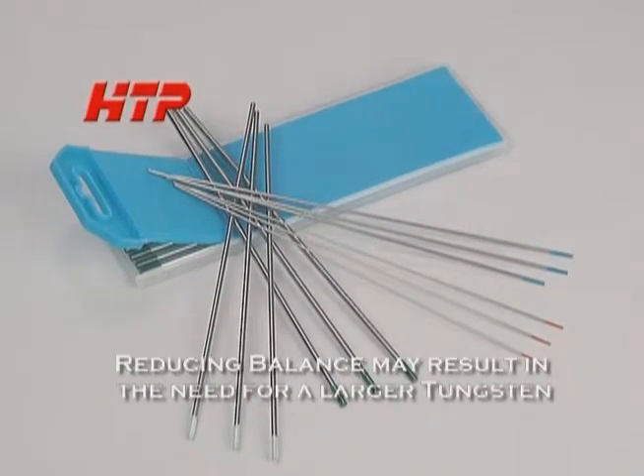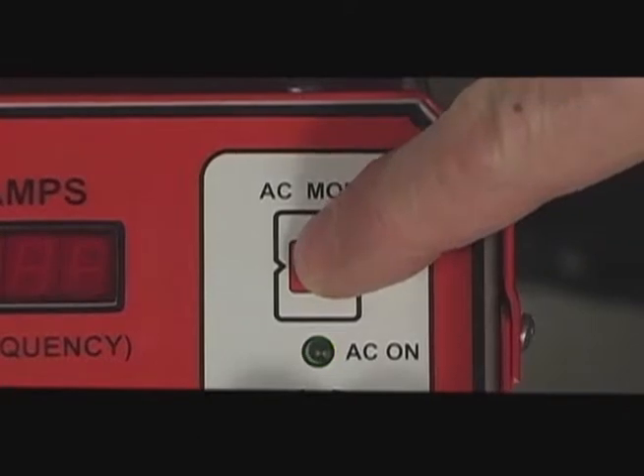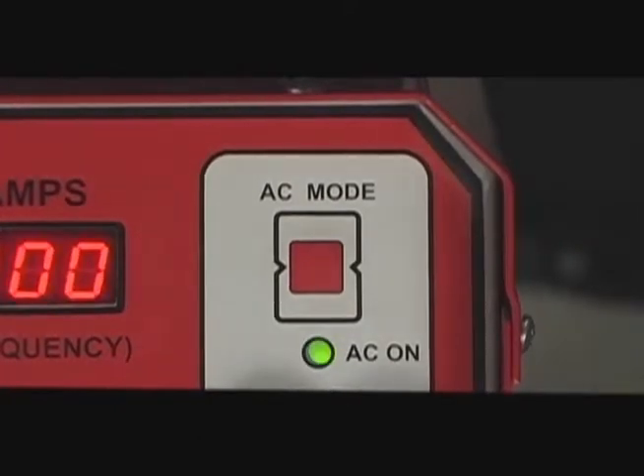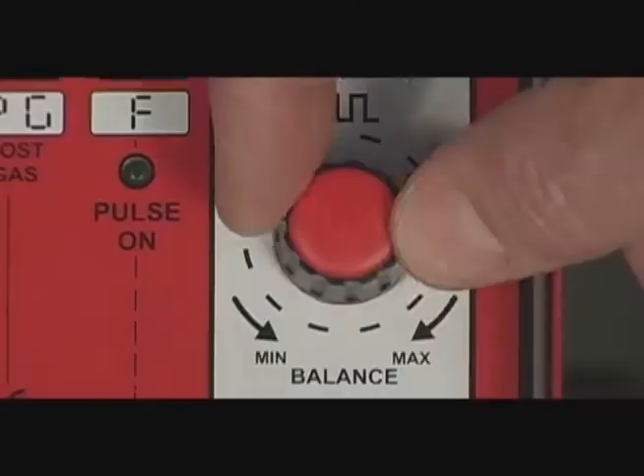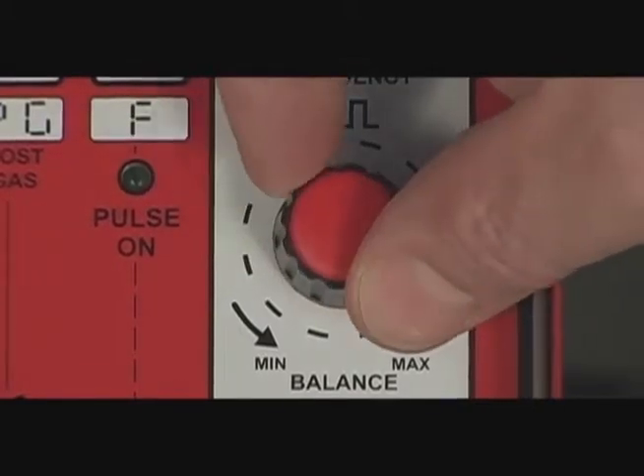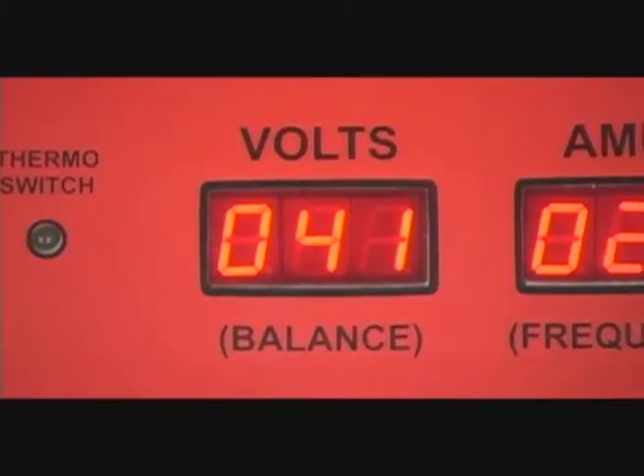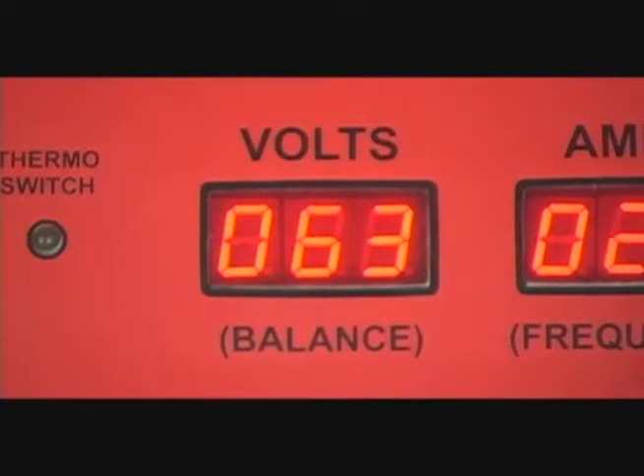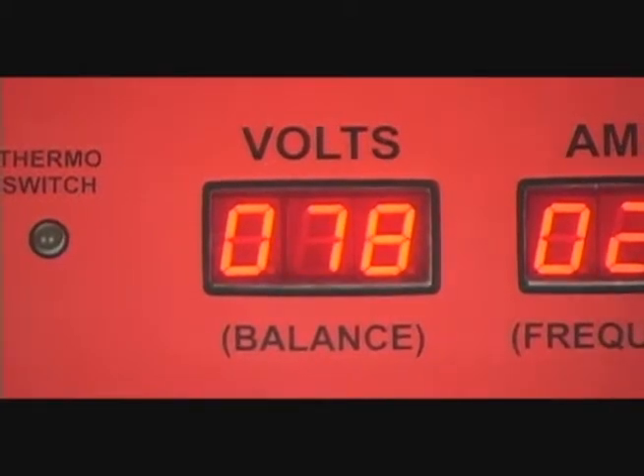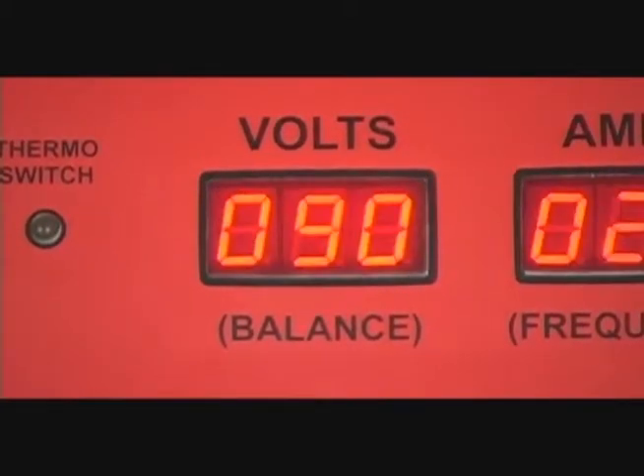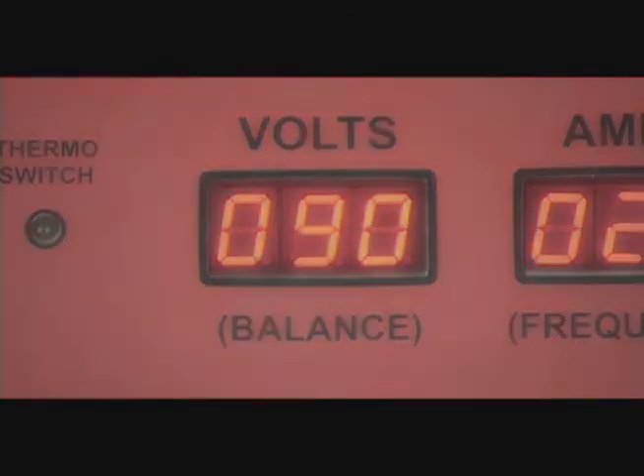You can adjust the balance when the machine is in the AC mode. Simply turn the balance knob, the volts display flashes and shows the balance in percent. The Invertig 201 allows you to adjust the AC balance from 10 to 90%, over a substantially greater range than is possible with conventional transformer units, 40 to 60%. So remember, higher balance, more penetration, lower balance, more cleaning.